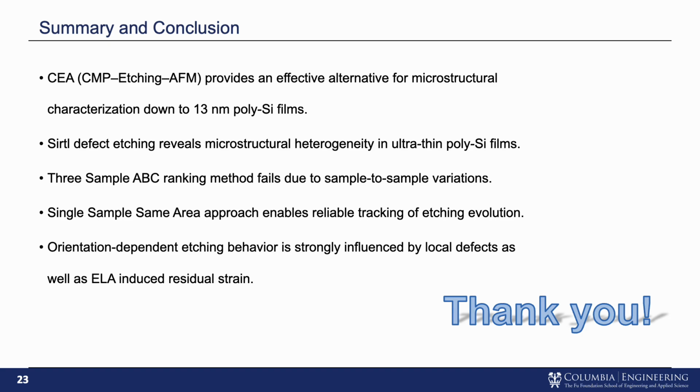To summarize, in this work, it's demonstrated that the CEA approach, combining CMP, defect etching, and AFM, provides an effective way to characterize microstructural features in ultra-thin polysilicon films down to 13 nanometers. By applying stir defect etching, we were able to clearly reveal microstructural heterogeneity. Grain boundaries, orientation boundaries, and twinning-related features all show distinct and time-dependent etching behaviors.